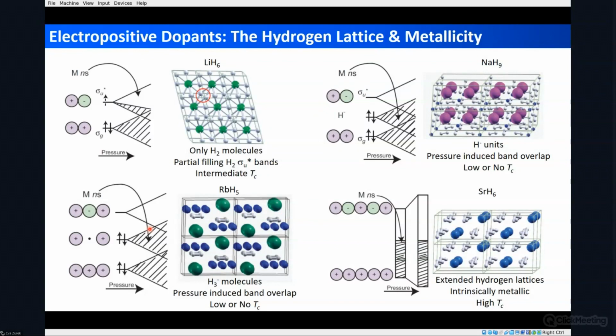And again, the TC is not going to be high because the density of states at the Fermi level is not high. However, what we see as the best candidates for metallization are ones that would be similar to this one-dimensional hydrogen chain that I talked about at the beginning, which is going to be a good metal even without donation from any sort of other element. So here I show a predicted SrH6 phase that has exactly such a one-dimensional hydrogen chain. It's a good metal, and it has a high TC, but you can actually increase the TC if you increase the dimensionality of the extended hydrogen network.